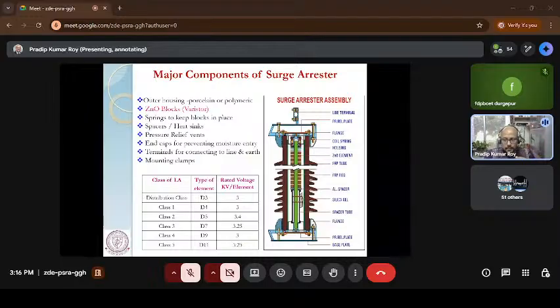Then the blocks are there, and in between the blocks there should not be any gap. If any gap is there, there is a chance of flashover through it. So you have to clean it, or make the surfaces so parallel that there is no uneven surface between the top and bottom surfaces. In between these two blocks, there is an aluminum spacer, and if the blocks are filled up and some portion remains, that part is filled up by the aluminum tube.